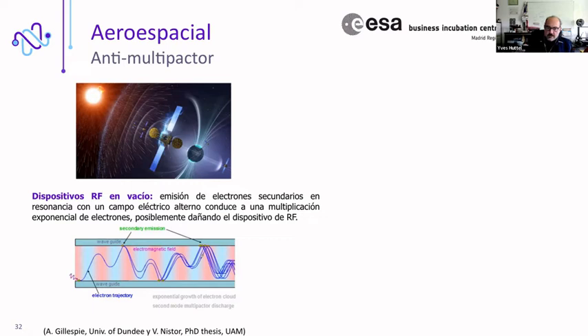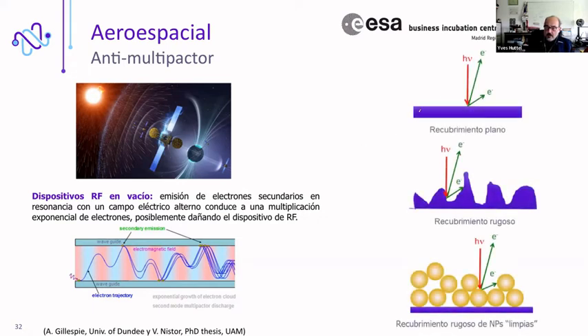So this has been a problem, and many have tried to find a solution. I've shown here the example where a high energy photon impinges on the surface of your device, it can emit electrons that have not stopped, and then you eventually have the cascade I was talking about. If you have a more irregular surface, you might be able to capture the electrons and avoid the cascade. So our proposal was to make a kind of nanostructured coating made of nanoparticles in order to stop the emission of the electrons.